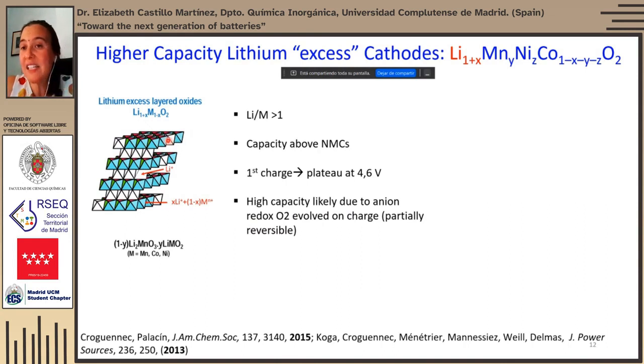Surprisingly enough, this gives capacities which are above the capacities of the NMC compositions, and also a very large plateau on the first charge at about 4.6 volts versus lithium. And there is a lot of discussion about this, and it seems that the most agreed argument is that the high capacity is likely due to anion redox on the oxygen sublattice. But this is an issue because the oxygen can evolve. And although in the bulk of the particle the oxygen is not released, it just reacts kind of reversibly.